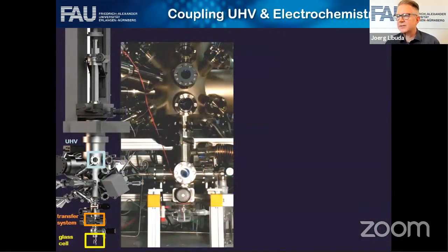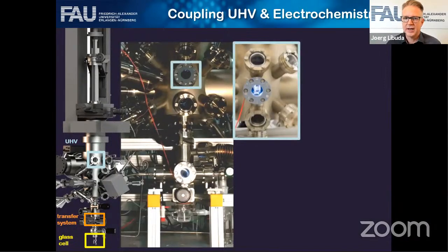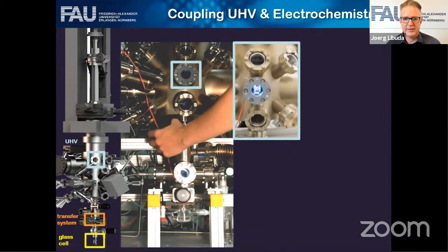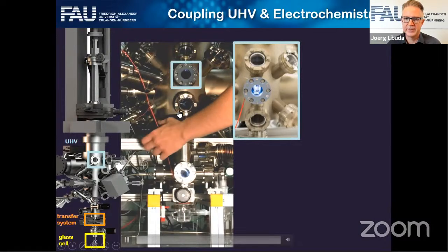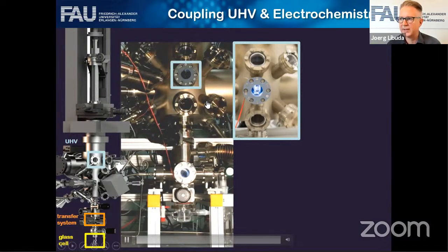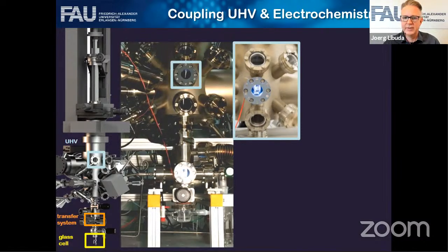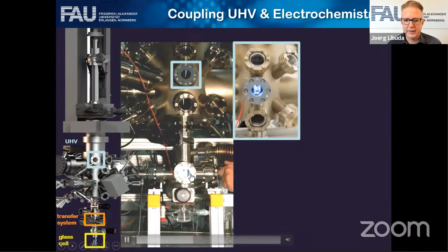Now, let me explain how such a system makes it from this very different vacuum environment into the solution. So this is the experimental system that we're using to transfer these model systems from the vacuum into the electrolyte or liquid environment. So this is the vacuum chamber where we prepare and characterize the sample, then it's moving down here into this lock. In this lock, it's automatically sealed from the vacuum chamber. Then you can fill this lock with ultra-pure gases, for instance, argon.